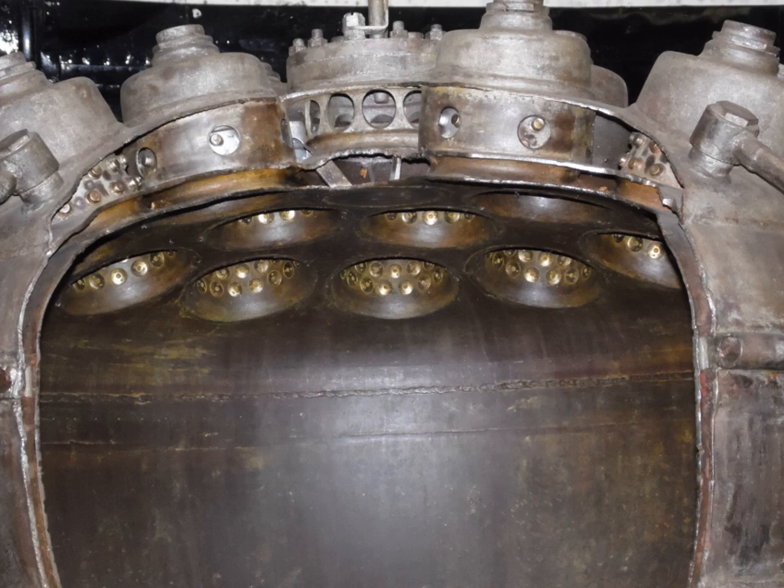With regenerative cooling, the pressure in the cooling channels is significantly higher than the chamber pressure; hence the inner liner is under compression, while the outer wall of the engine is under significant hoop stresses. The metal of the inner liner is greatly weakened by the high temperature, and also undergoes significant thermal expansion at the inner surface while the cold side wall of the liner constrains the expansion. This sets up significant thermal stresses that can cause the inner surface to crack or craze after multiple firings, particularly at the throat. The thin inner liner requires mechanical support to withstand the compressive loading due to propellant pressure; this support is usually provided by the side walls of the cooling channels and the backing plate.